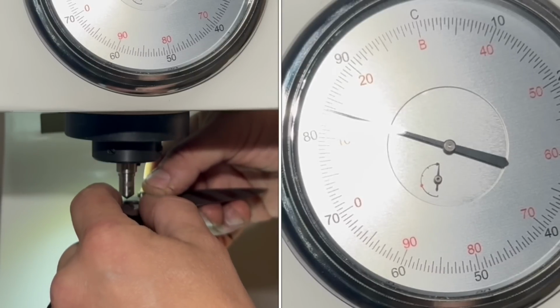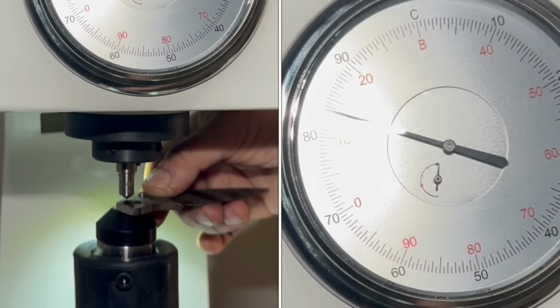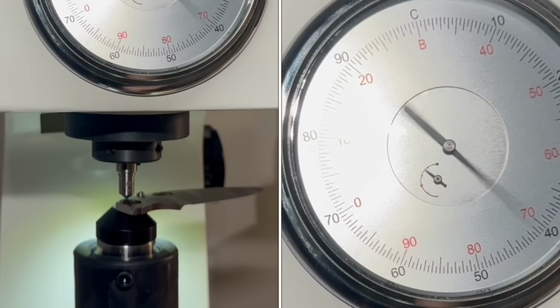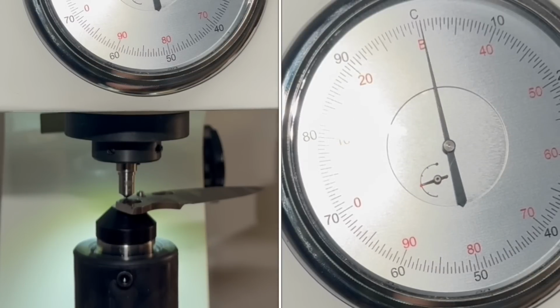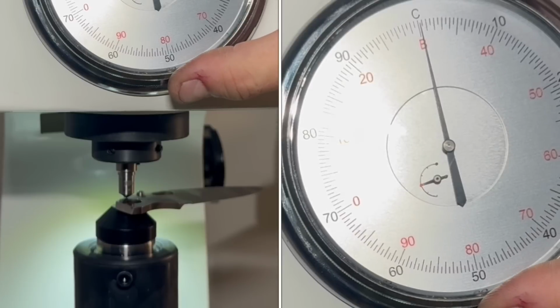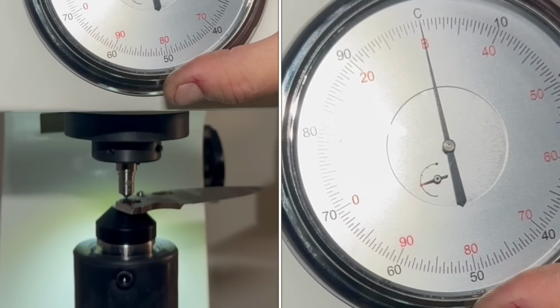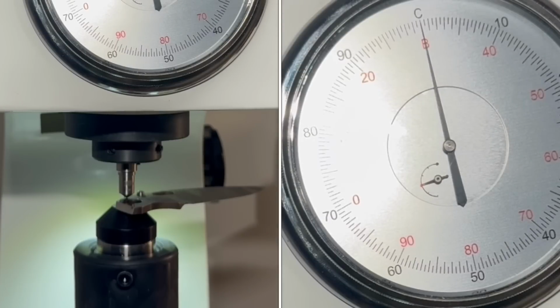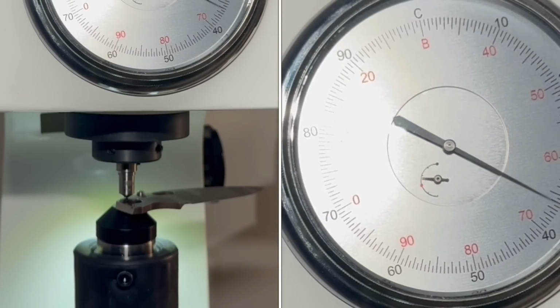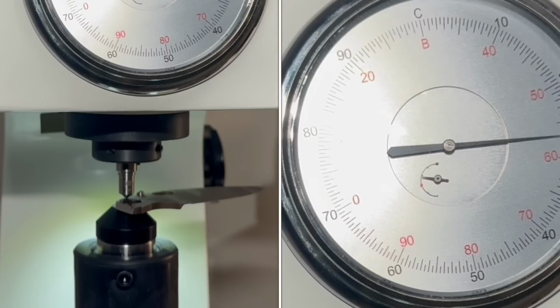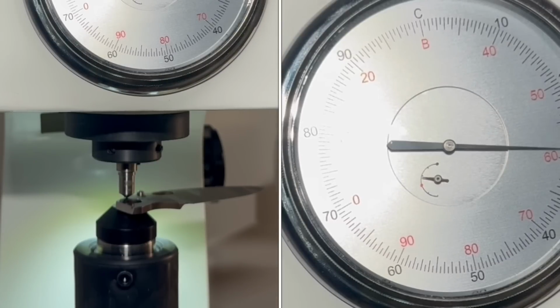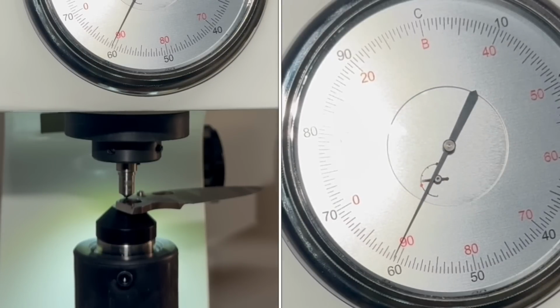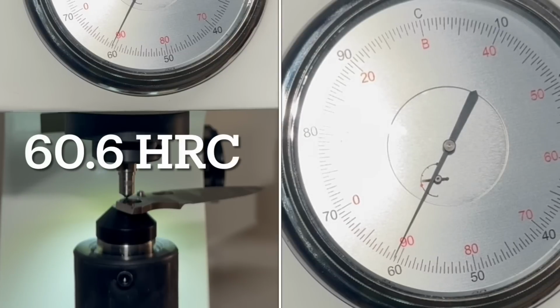So let's talk about this specific blade. As you recall, it has HC treatment, which stands for heat coloring, and then the tiger stripe pattern is applied via Cerakoting. Both of these processes require application of heat, post-heat treatment. So typically, unless the bladesmith plans to heat treat a little bit higher so that they can apply those heat processes, the blade's hardness drops by up to 1 point HRC because it's like an additional tempering. Being one of the top most stainless steels in the world, MagnaCut doesn't really require extra finishing. And yet again, we're at 60.6 HRC.